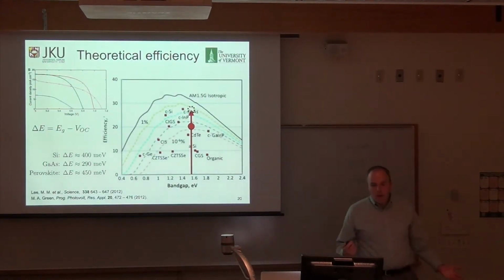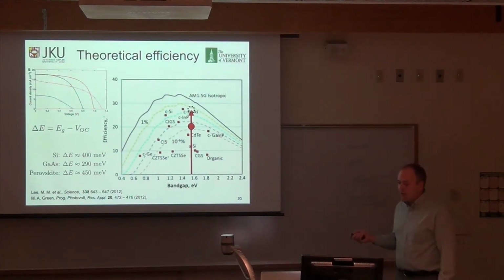So if the efficiency is already at 20%, what are we still trying to do? Well, there's a few things. One exciting thing is that this MAPI material has a band gap of 1.55 eV, with efficiency around 20%. But if we look at the loss in voltage, silicon has about 400 meV, gallium arsenide about 300, and perovskites between 350 and 450. That means in terms of radiative quantum efficiency they should be very good, so the theoretical limit should be somewhere right next to gallium arsenide or crystalline silicon. Just based on the material itself, we think we can get that efficiency up higher.